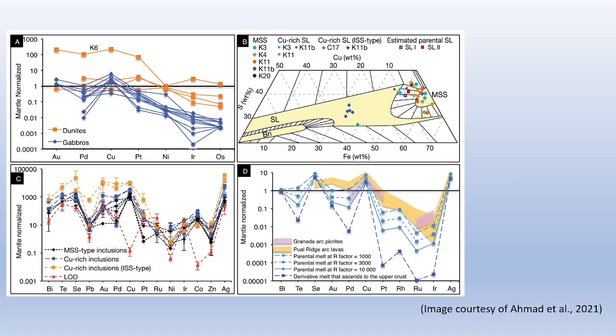But even after this deep filtering, the melt still carries about 50 ppm copper, which is more than enough to generate porphyry copper deposits. What is unusual here is that this massive metal depletion takes place entirely in the deep crust. It doesn't require a second stage of remobilization or fluid saturation at shallow levels, which is the backbone of many Andean style porphyry models. Instead, the lower crust itself acts as a powerful metal filter, stripping magmas of their PGEs and gold long before they reach levels where ore deposits form.